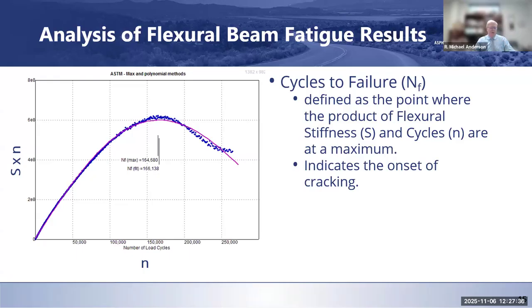It did seem to work reasonably well for unmodified materials. As we started using more modified materials, as different types of materials came on the market, it was not necessarily representative. And some work that was done by Dr. Jeff Rowe with Abatech and I think Dr. Mark Bolden, who may have been with Koch or Shell at the time, I'm not sure which, looked at a new way of defining failure. It has to do with the point where the product of flexural stiffness times cycles was a maximum, and that indicates the onset of cracking. If you plot that against the traditional way of looking at it, for unmodified asphalts it tends to be right around 50% still, but for modified asphalts it does a much better job of characterizing that material.